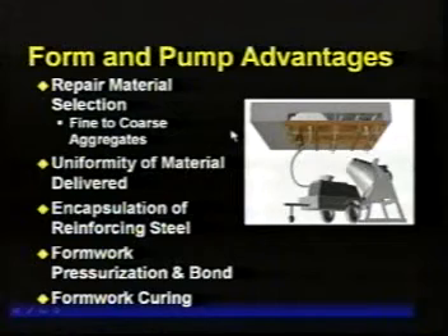We actually pressurize the form, and that pressurization is what consolidates the material around the reinforcing steel and drives it into the pore structure of the existing concrete, resulting in a good bond. So that's what this technique is. It's very similar, same kind of preparation technique. We're building formwork that will resist the pressure and will have some kind of connection to the pump line, which I'll show you in some slides in a moment.